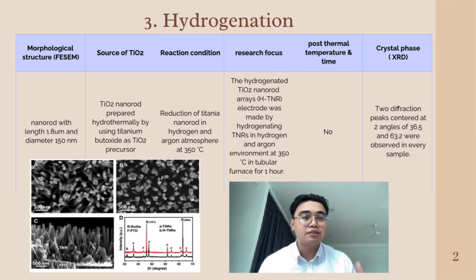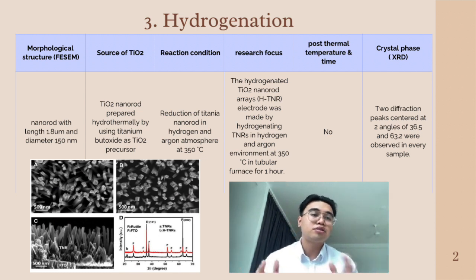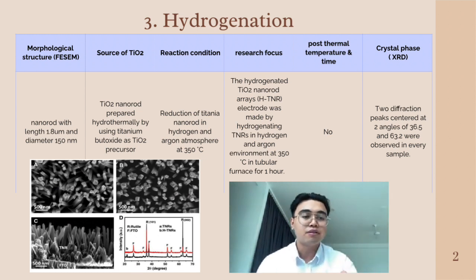The third method is hydrogenation. Morphological structure in this step: after the hydrogenation in figure A and B, it shows no notable surface morphologies. In figure C, the TiO2 nanorods with average diameter of 150 nanometer and length of 1.8 micrometer cover the whole FTO structures. And the result in XRD patterns before and after the hydrogenation shows no phase shift following the hydrogenation, whereas TiO2 peak intensity reduces. In hydrogenated TiO2 investigation, its defect density increases.